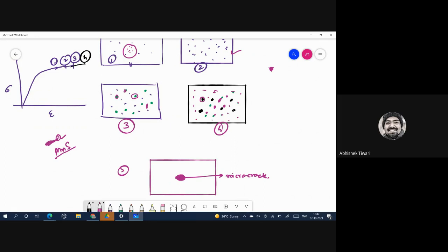And precipitates usually are not in that bad shape because they emerge out of the material. This one is there because of a manufacturing defect, because some oxides or sulfides got trapped during the making of steel. So when you have manufacturing defects in the form of inclusions, oxides, or graphite in cast iron, this phenomenon of more damage at the center will shift to the area where you have the inclusion. So if the inclusion is here, you will see bigger voids coming up next to it instead of at the center. This micro void will form here rather than at the center.